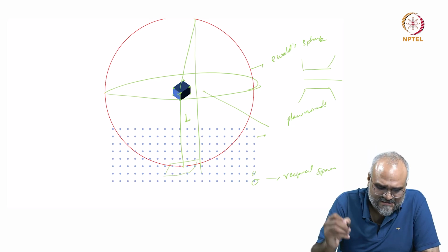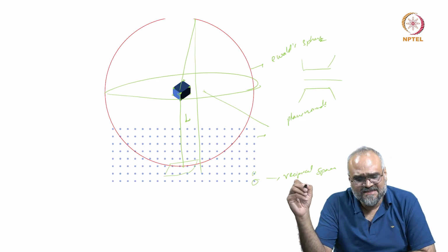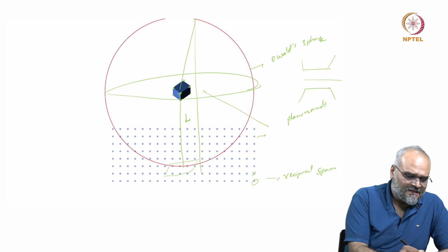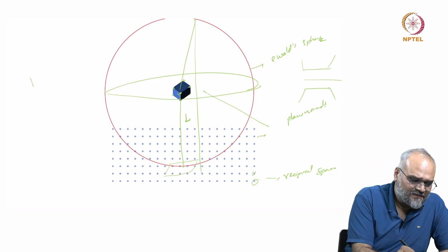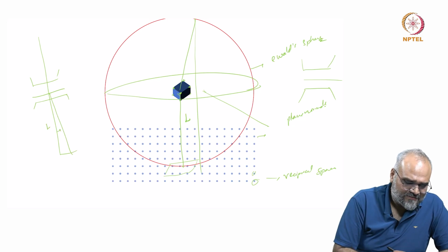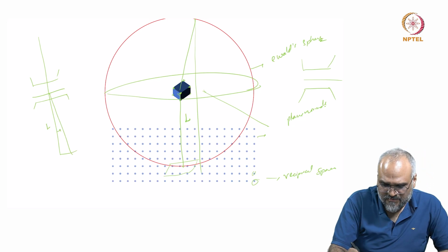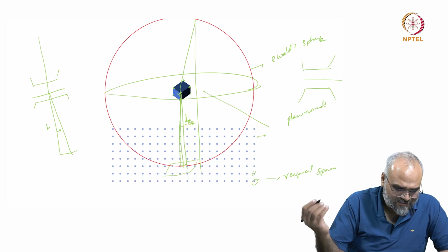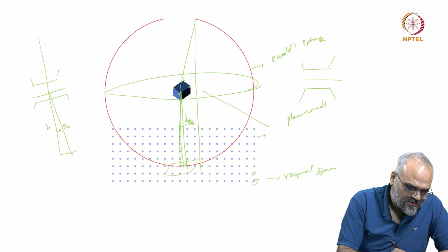This particular distance I can measure in terms of the camera length, and now in a TEM, let us say if I have the construction like a lens and then I have a specimen here and I am now recording a diffraction pattern at a length L, and let us say from the central beam to get a diffraction spot over here, I have to scatter through an angle theta B1, and let me call this the Bragg's angle 1.